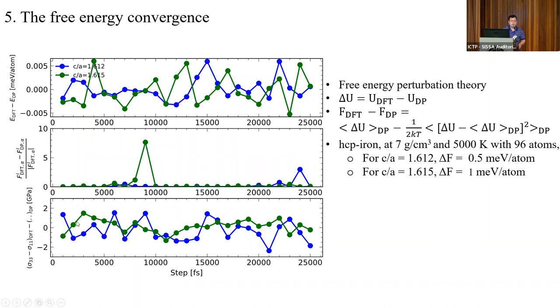We also compare the relative force error, which is very consistent between the DFT and DP model. Another important property is the difference (σ₃₃ − σ₁₁) between the DP model and DFT. This quantity is important because for an anisotropic solid phase you need very accurate cell parameters; otherwise, during thermodynamic integration for the solid phase there will be extra elastic energy that corrupts the phase diagram calculations. From our study this difference is within about 2 GPa and the absolute value is around zero.